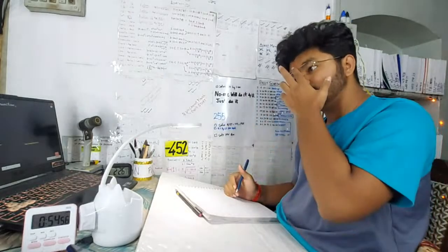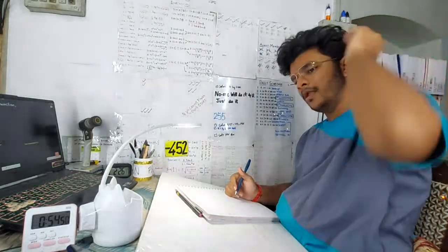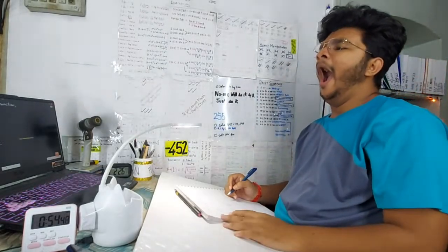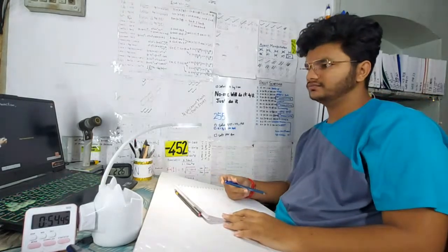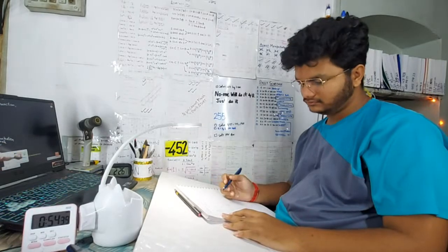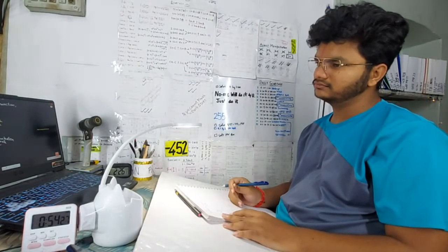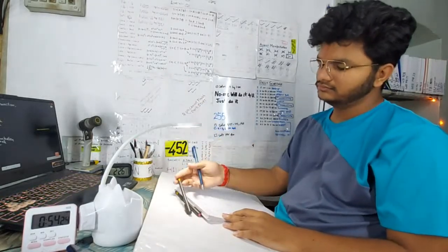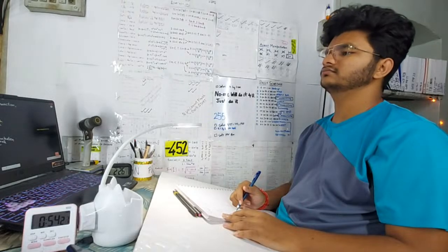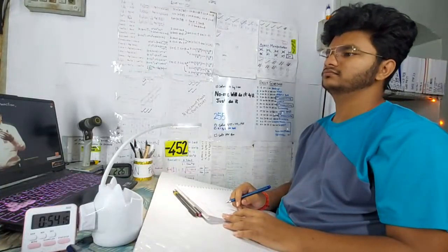Now you can identify that any transformation normally will be like this. With decrease in temperature, the nucleation rate keeps on increasing. This graph shows the variation of nucleation rate. Whereas I try to show you another graph. That is, with the decrease in temperature, growth rate keeps on decreasing like that. This graph indicates what is called as growth rate. Now, with the decrease in temperature, nucleation rate increases. With the decrease in temperature, growth rate decreases. These are essentially two components of overall transformation rate.